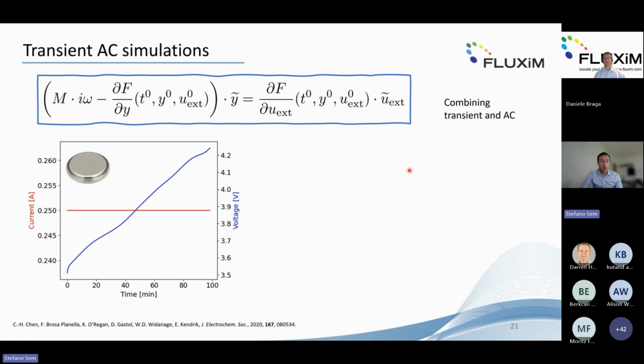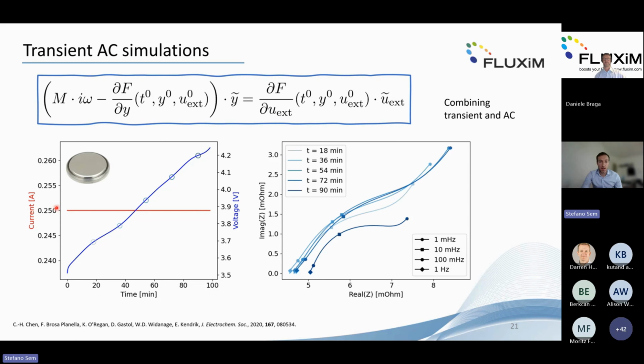We also made simulations combining the transient, but also AC. So here is a transient, which is a charging curve of a battery. You see the voltage is increasing when you charge with a constant current of 0.25 amps. And here we can already do simulations of the impedance data at certain points. So here, after 18, 36, 54, 72, and 90 minutes of charging, we have an impedance simulation. These are very, very fresh results of Setfos.